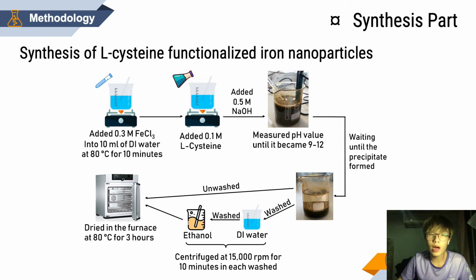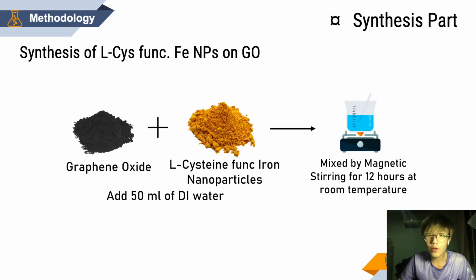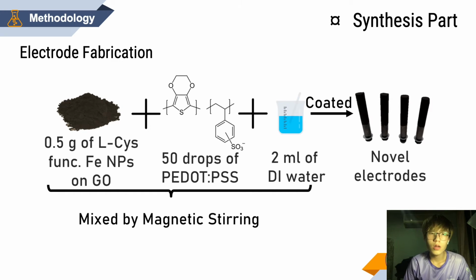We start by using the iron colloid and mixing it with the L-cysteine, and then we adjust the pH of it, and finally we will get the L-cysteine functionalized on iron nanoparticle. After we receive the graphene oxide and L-cysteine functionalized on iron nanoparticle from the previous process, we mix it together with magnetic stirring for 12 hours at room temperature, and finally we will get the final products.